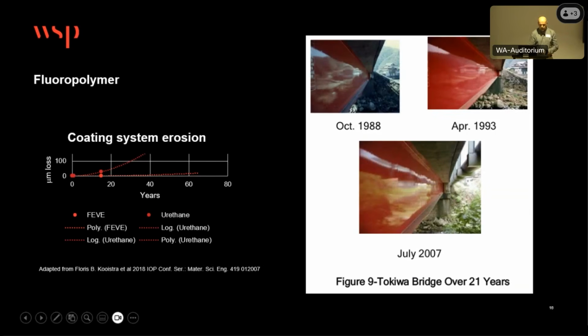And when compared to a typical polyurethane, the fluoropolymer has showed marked reductions in film erosion, particularly when exposed to high UV radiation, and also salt spray consistent with a tropical island exposure, with average degradation rates suggesting we could get a film service life of at least 100 years from just 25 microns of coating, in theory. In practice, we'll go through that.